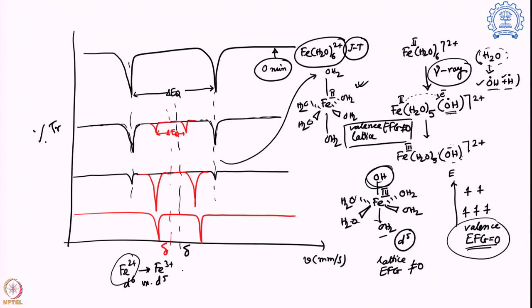And that is actually affecting the overall isomer shift, because we know the s electron density, psi 0 square, is going to multiply with delta R, which is negative in nature. So this psi 0 square will be higher in the case of D5 or the iron 3 plus system, because it has more chance to see the nucleus, and this delta R value is negative, so it is going to shift more on the negative side. So that is why we are seeing this particular change over here, that slowly the delta EQ value is shrinking down and also shifting towards the negative direction.